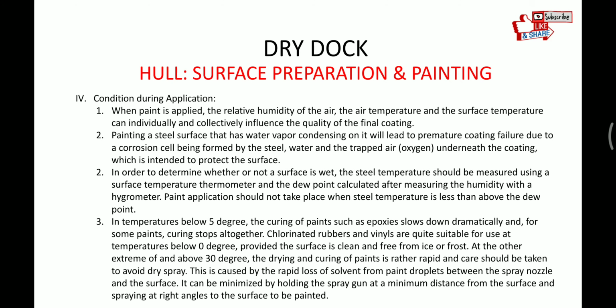Now let's see the conditions during application. During application, when paint is applied, the relative humidity, the air temperature, and the surface temperature can individually and collectively influence the quality of the final coat. Painting a steel surface that has water vapor condensing on it will lead to premature coating failure due to a corrosion cell formed by the steel, water, and trapped air underneath the coating. In order to determine whether or not the surface is wet, steel temperature should be measured using surface thermometers and dew point calculated after measuring the humidity. So paint application should not take place where the steel temperature is less than the dew point.